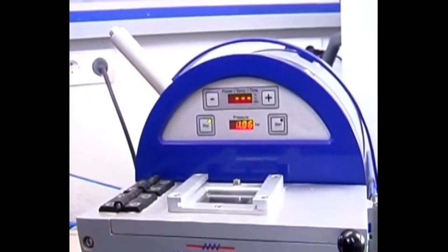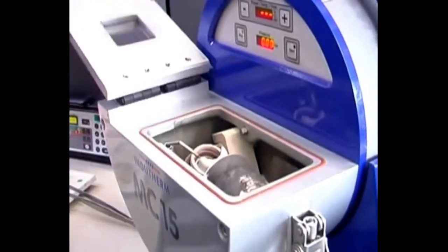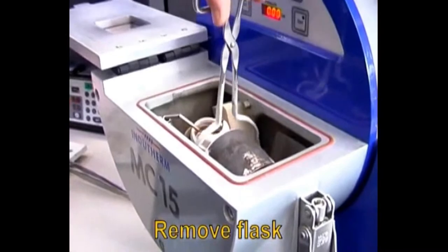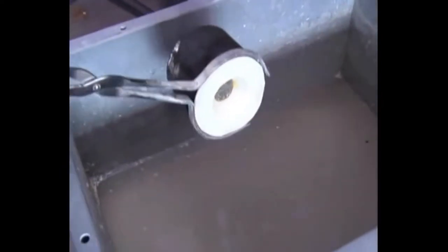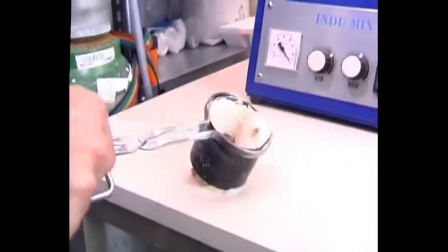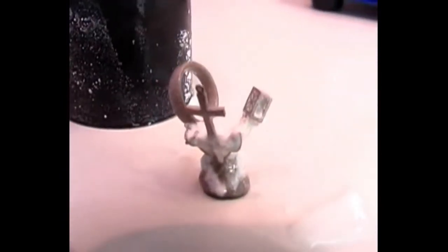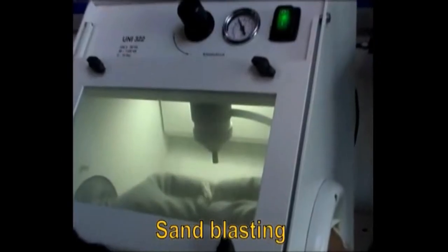Then we wait about 10 to 15 minutes for the metal to cool enough to take it out — it's still super hot, probably still about 600 degrees. Now we de-vest: remove the investment. For gold and silver it's very easy — just throw it in a bucket of water. Because it's hot and the investment powder is water-soluble, the hot water with lots of bubbling basically dissolves the investment powder again, leaving us with the metal pieces. Sometimes there's leftover investment powder — you can use a sandblaster to remove it quickly, or a toothbrush if you have more time. You can now see the finished material.